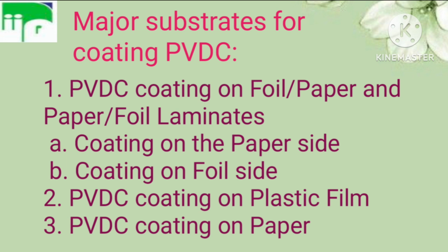By itself, a foil paper or paper foil combination offers absolute protection against light and thermal conduction. However, this lamination still cannot provide good protection against penetration of moisture, gas and aroma. Hence, heat sealable PVDC lacquer is recommended to get optimum barrier properties. It is also of two types: coating on the paper side. Normally 9 to 10 micron de-oiled aluminum foil is the base material, the outside of which is lacquered with wash primer to facilitate the printing, while the inner side is laminated with super calendared, wood-free, bleached kraft paper of 40 to 80 GSM. This paper is then coated with PVDC.